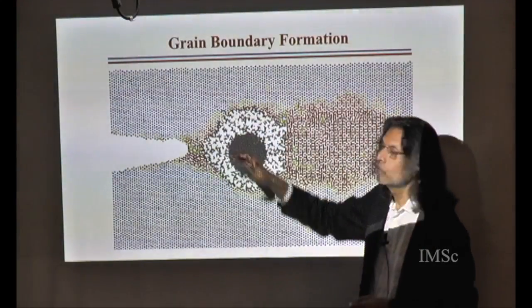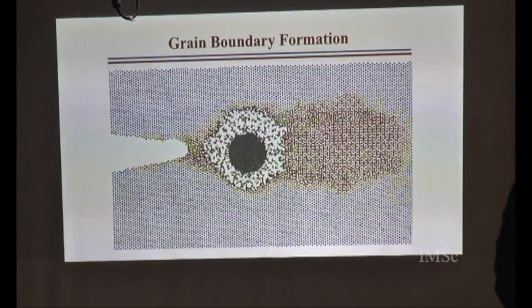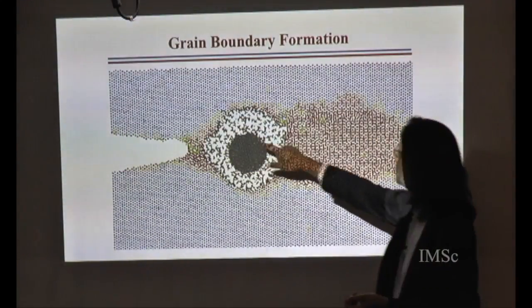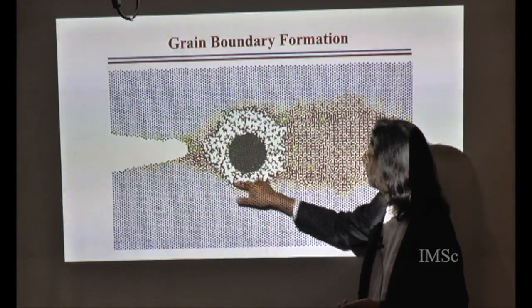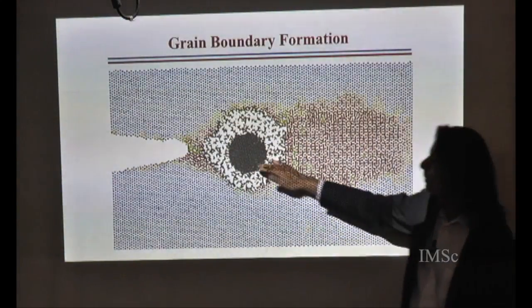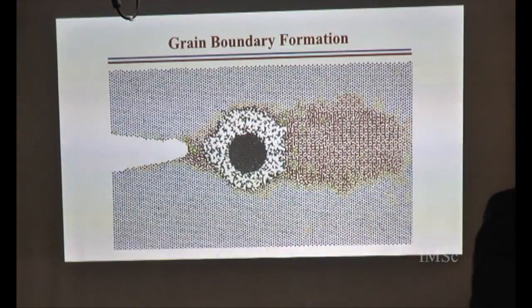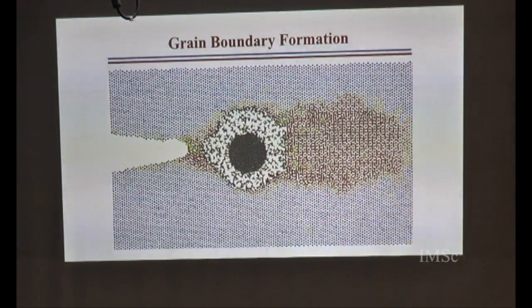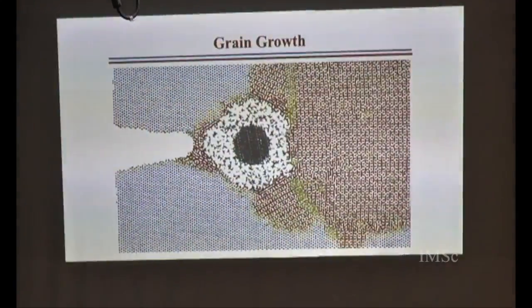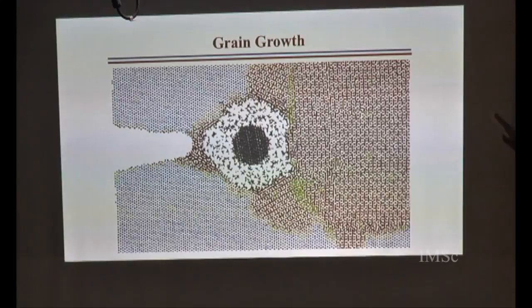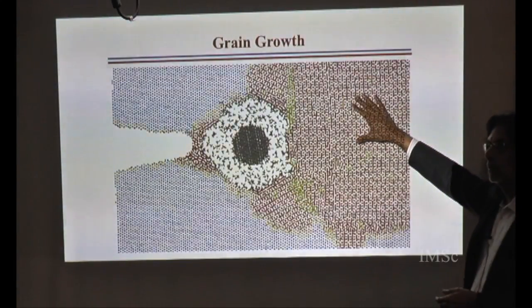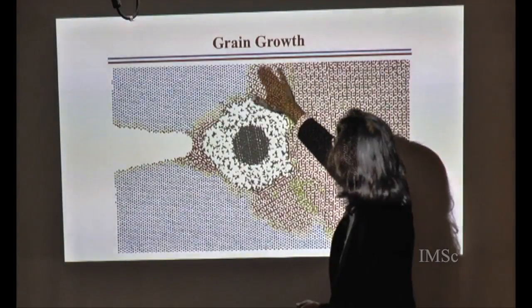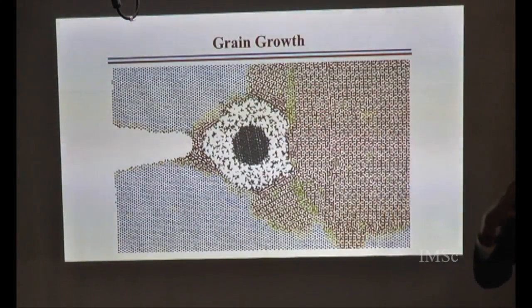And in addition, what we see is we started with a spherical nanoparticle, and then there is a phase transformation where you begin to see faceting of these nanoparticles. So these are facets in the system. And this is where the silica is flowing into the crack and stopping it. So this is a snapshot at one strain. If you keep increasing the strain, you begin to see how this damage zone grows, but still no cracks over here. And then you have this grain growth and grain boundary formation.